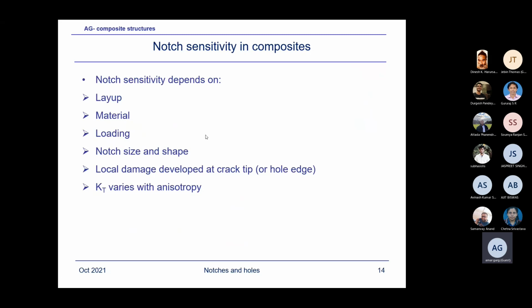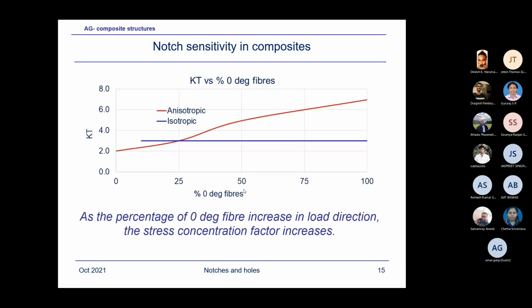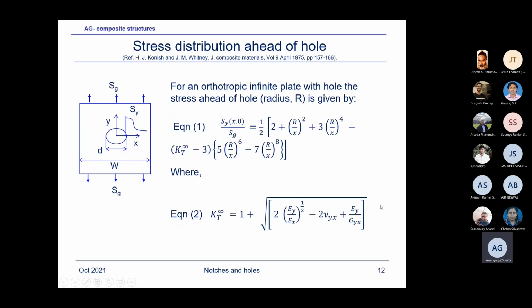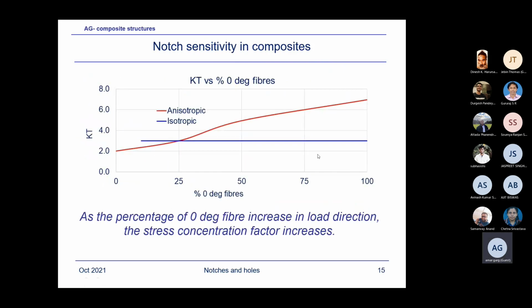Okay, notch sensitivity in composites. So notch sensitivity, because the laminate or the material is sensitive to the notch, and the notch sensitivity depends upon the layup, material, loading, notch size and shape, and local damage developed at the crack tip at the hole edge. KT varies with anisotropy. I've just shown, based on this equation, KT infinity, to try to give you an idea how the KT, which is 3 for the isotropic material, as you can see here, this is the 3 value for isotropic or quasi-isotropic material.